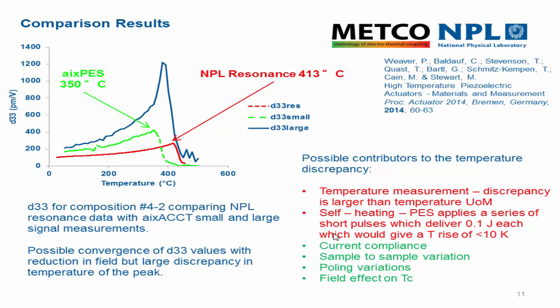One of the things that you may have noticed, because I've put some big arrows on it, is the temperature differences. There are discrepancies in the temperatures of the peaks between these different measurement results. And we're not quite sure why that is. We've looked long and hard at the temperature calibrations in these different systems, and nothing we can find there explains this discrepancy. So it's larger than the uncertainties in the temperature measurement.